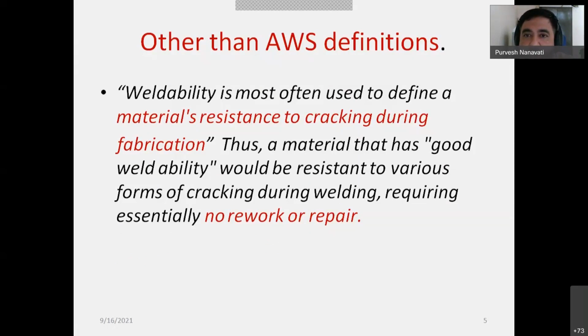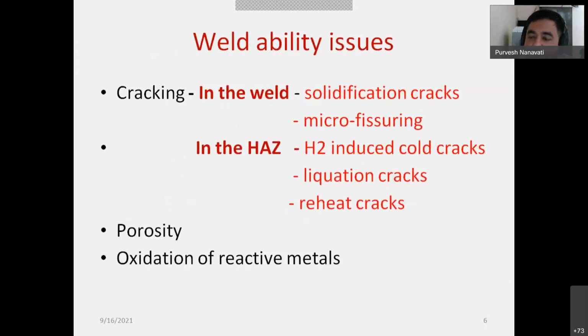Then, okay, let us go through some issues in weldability. I am not sure whether the previous speakers have told sufficiently about the weldability issues, but I have thought to slightly touch upon those things to understand the tests of weldability and quantification. In the previous slide, I came across the term resistance to cracking. Now, the cracking can be in the weld or in the heat affected zone. If the cracking is in the weld, it is most of the time known as solidification cracking or micro fissuring. And if it is in the heat affected zone, it may be due to hydrogen induced cold cracking, known as hydrogen embrittlement cracking, or maybe because of liquation cracks or reheat cracks.